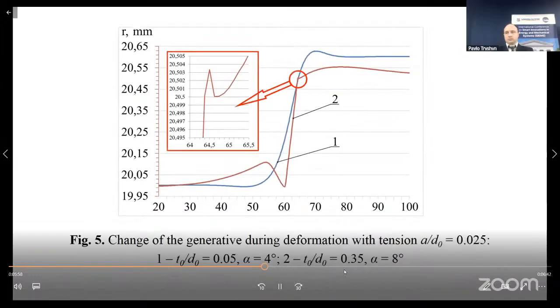The simulation results, figure 5, show that the change in the generatrix function for the thin-walled part, curve 1, is smooth and differs from the change in the generatrix function for the thick-walled part, curve 2. It should be noted that the height of the non-contact zone behind the contact zone for the thin-walled part is significantly higher than the height of the non-contact zone for the thick-walled part, and the length of the contact area for the thick-walled part is significantly longer than for the thin-walled part. As follows from figure 5, curve 2, the contact zone has two areas of local plastic deformation. For clarity, curve 2 is presented in an enlarged scale.